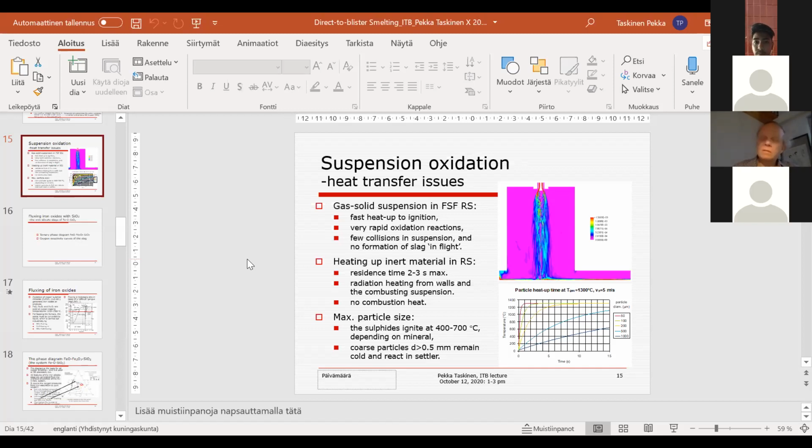As I said, typically in the first furnace you are taking out only copper, which is then fed into the anode furnaces, and the second step of slag cleaning makes, they are actually calling it matte, but it doesn't contain much sulfur. So a metal phase, which is rich in iron, containing 30-40% iron, and then some copper, and depending on what you are taking out from the slag, nickel, cobalt, and so on. Polish smelters are taking lead in this step from the slag.